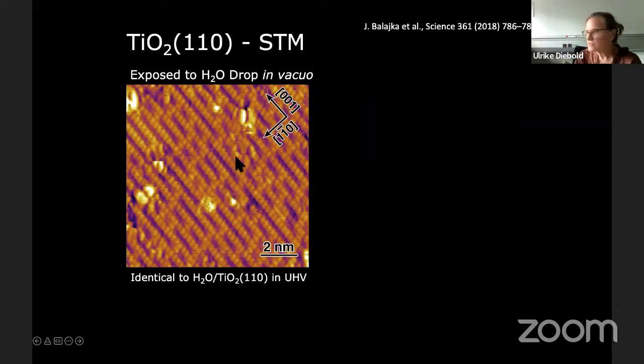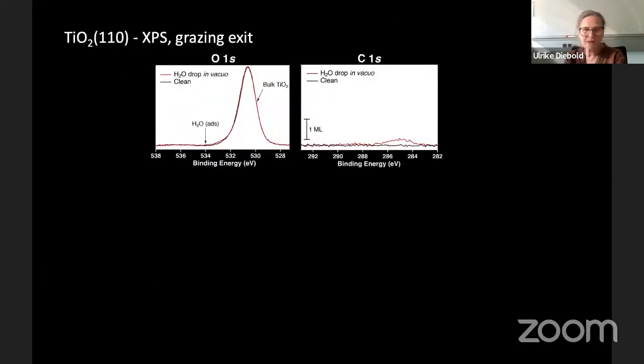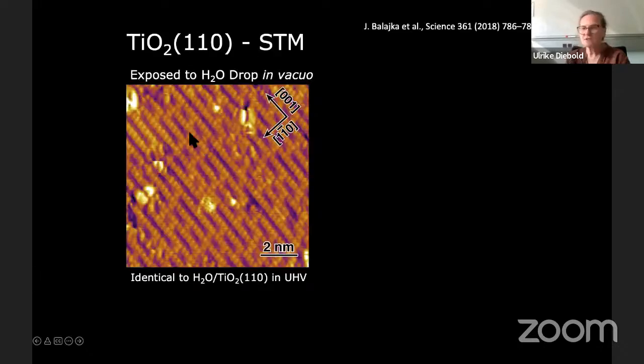So this is the TiO2 surface I showed you in the beginning. These are the titanium rows. Here, single hydroxyls. There's a little bit of dirt, but very little. It's essentially identical to a surface that has been exposed to a little bit of water vapor in ultra high vacuum. So it's really very clean. And I can tell you this is exactly the structure that we had before. Nothing has changed on this TiO2 110, which is the lowest energy surface.